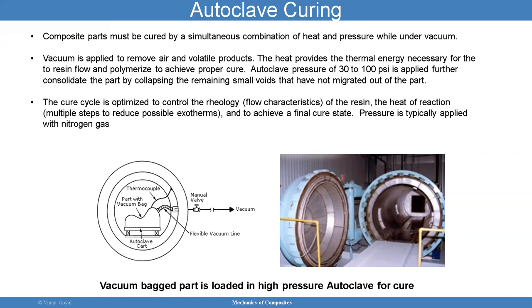Composite parts must be cured by a simultaneous combination of heat and pressure while under vacuum. So you definitely want to apply heat and pressure under vacuum. The vacuum is applied to remove air and volatile products, while the heat provides the thermal energy necessary for the resin to flow and polymerize to achieve proper cure. Autoclave pressure of 30 to 100 psi is typically applied. So that oven right here is applying pressure to further consolidate the part. What you're trying to do is collapse the remaining small voids that have not migrated out of that part.